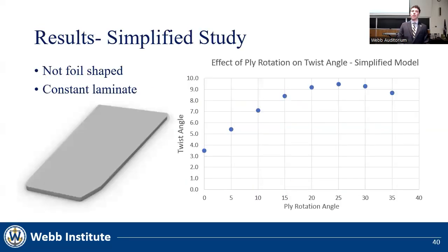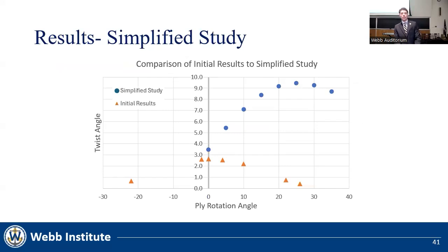To begin analyzing what went wrong with our initial study, we performed a simplified study. This utilized a centerboard that did not have foil-shaped cross-sections. For this analysis, we also kept a constant laminate at different ply rotation angles. We did not adjust the thickness to maintain a safety factor. This model behaved more as expected, showing minimum twist at a 0 degree ply rotation angle and a maximum twist at a 25 degree ply rotation angle. For reference, here are the two results side by side. As you can see, our initial results did not behave at all as in the simplified study.